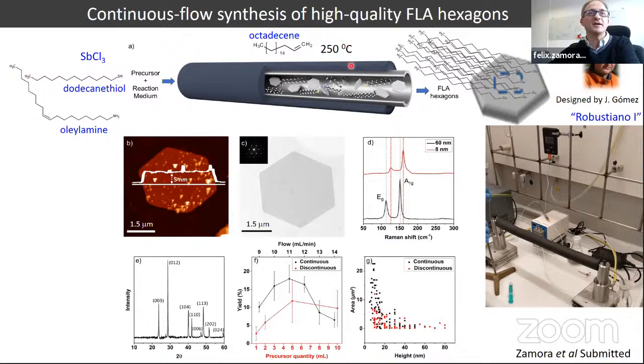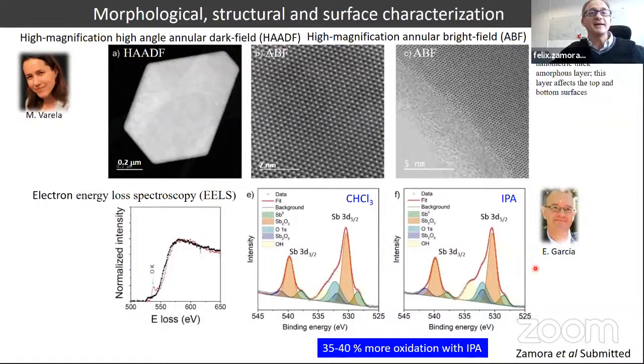Okay, but the question in all these syntheses is that we observe that as far as we are using these long molecules, these long thiols, at the end of the day, we form hexagons, but they are partially or sometimes fully covered by these long molecules. And this is a problem if you want to use these hexagons to build devices. You have to establish, for instance, electrical contacts. So here I showed you that we were evaluating the use of different solvents in order to remove this film on top of the hexagons. I show you here just two solvents, isopropanol, with which we were able to remove the film, but we induce a kind of oxidation.